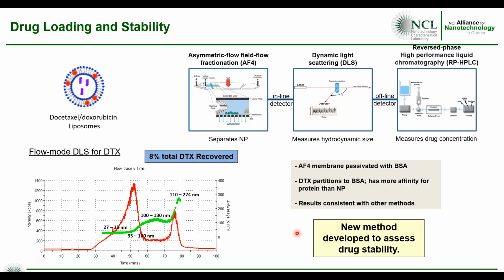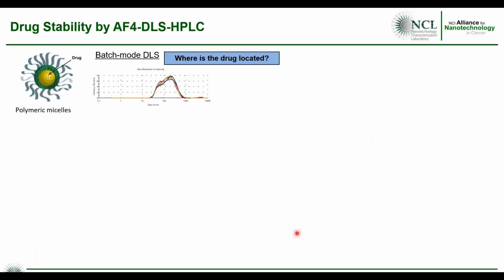What's nice about this is with 2 runs, you can do with and without protein or plasma protein incubation. You get size distribution of your formulation. You get drug distribution as a function of size. And finally, you get possibly drug stability of your formulation. So making AF4 a very nice method to use in characterizing nanoparticles.